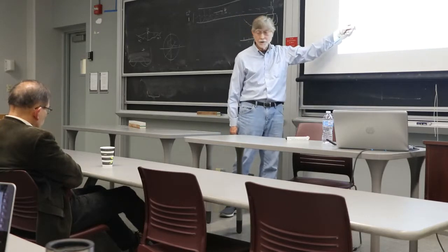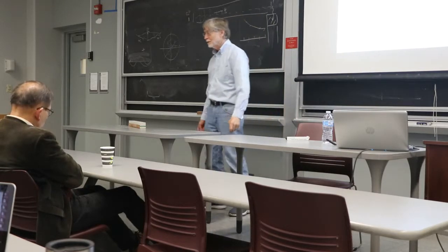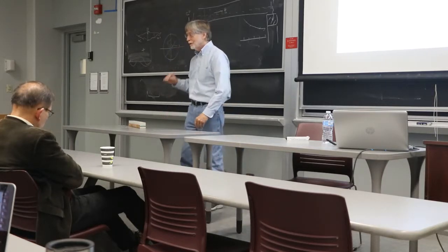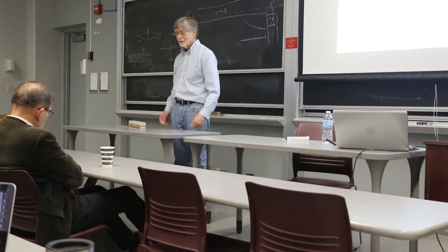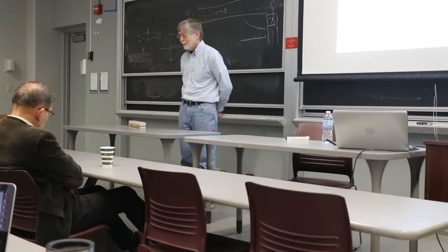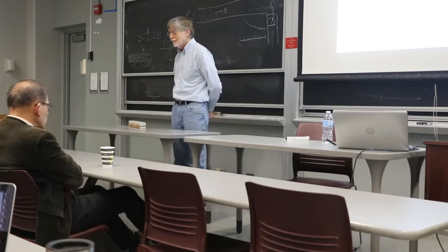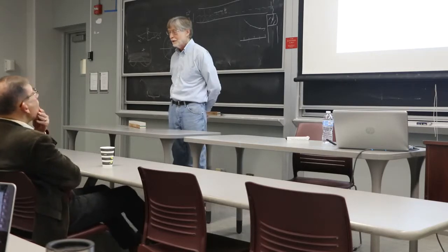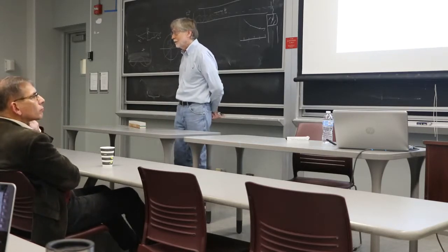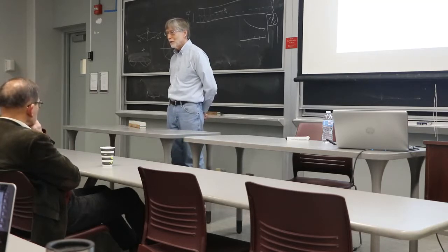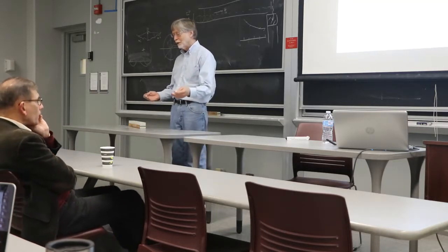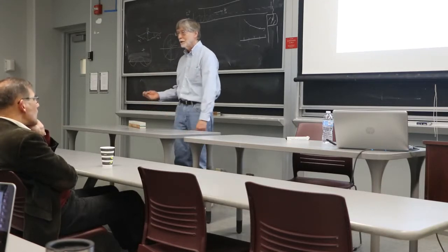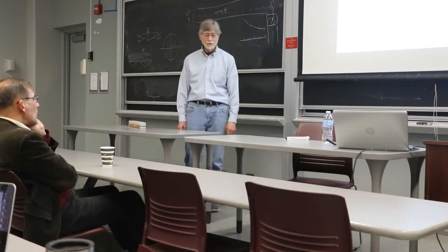So this guy, Cherry, he didn't even know about Madansky's paper because he was an electrical engineer, but he wasn't into the physics. But he published his paper in which he got 1 in 10 to the 8 positrons were coming out of a piece of chromium as slow positrons. And he got about 10 positrons per second. That was the first positron beam, the first time when you could have taken positrons of a known energy, put them into something, and learned something about the material alone, without the complications of the source.